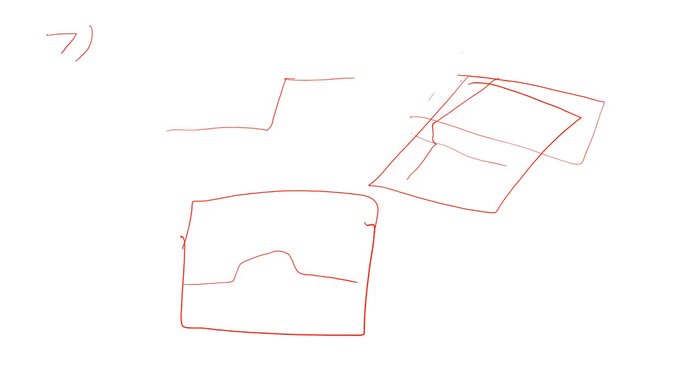is out of the plane, whereas a kink is in the slip plane. And kinking is how dislocations move. Because you've got your Peierls-Nabarro barrier, you have to overcome your Peierls stress, which if you do that for the entire dislocation line is hard. But I can move this part forward a little bit, and now my whole dislocation can move forward by this kink simply spreading laterally.